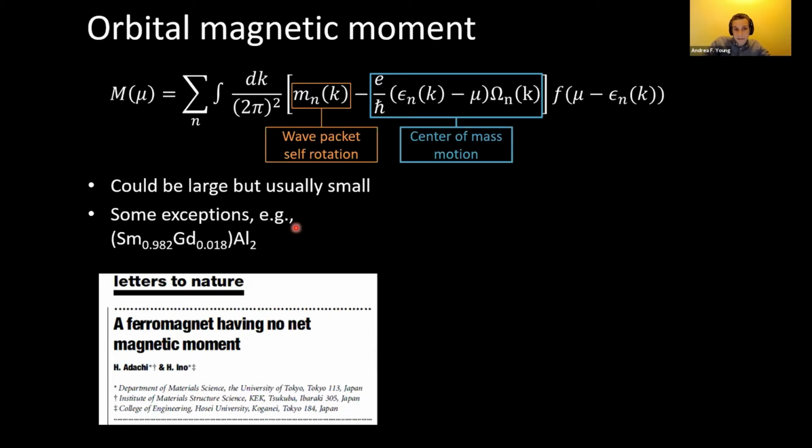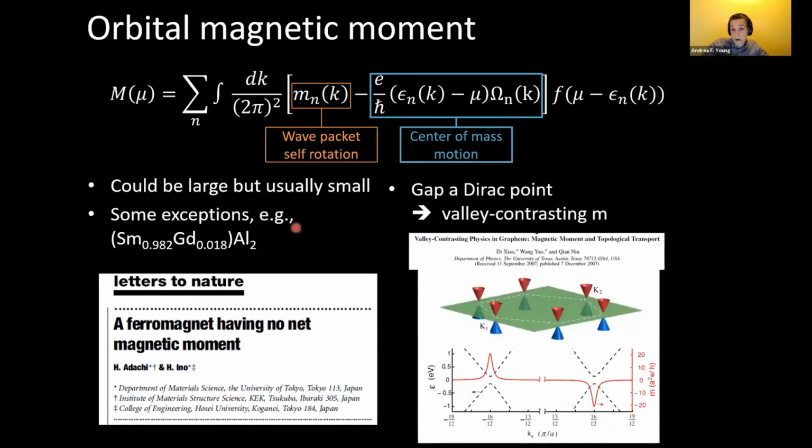That's different in graphene because of this absence of spin-orbit coupling, and also because it's a very natural way to generate large orbital moments. So, as was pointed out by Xiao and Niu, the valley in graphene, if you gap a Dirac point, naturally generates a large orbital moment right around the gap, and that basically arises from the strong Berry curvature that happens at that Dirac point.